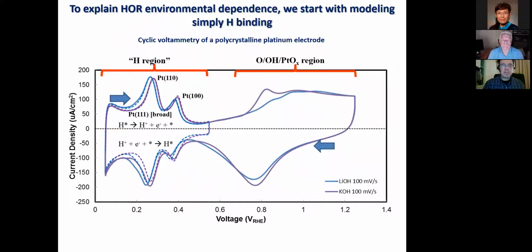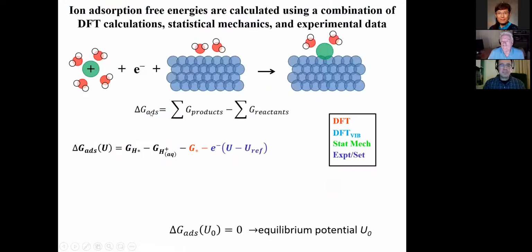So to be able to then simulate or understand what's going on in this experiment computationally, I need to know the thermodynamics of hydrogen going on and off the surface. Because these peaks are relatively symmetric, that's our electrochemical proof that we can really think of this as equilibrated. Even though we're measuring a rate, a current, what we're measuring really is the shift in equilibrium. As we make this electron more and more stable, we're watching the reaction shift to the right. And at each one of these potentials, we're approximately in equilibrium.